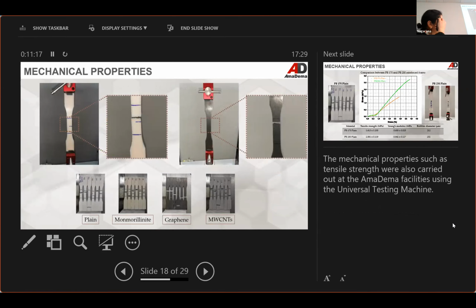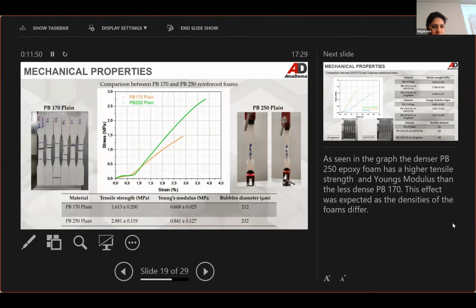Okay, so moving on to the mechanical properties, and in particular the tensile properties of the samples. We are following an ASTM standard, and we're using a universal testing machine with dog bone shaped specimens, and we have tested these to see how they respond in tensile. Starting from the two plain systems, we've seen that the system with the highest density, the 250 system, demonstrates higher tensile strength and higher Young's modulus. And of course, the bubbles incorporated are larger.